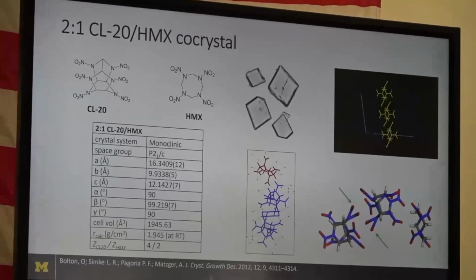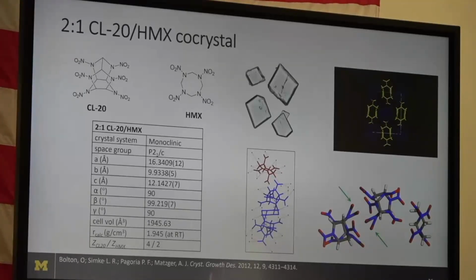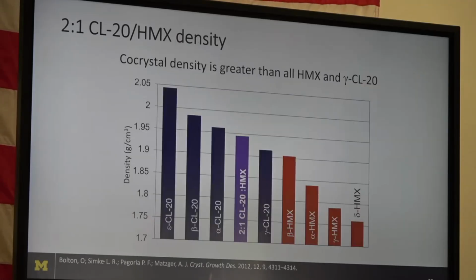The next really exciting energetic co-crystal that we made was CL-20 HMX. Now you're seeing an effect of stoichiometry. There are actually 2 CL-20s for every 1 HMX here. This is the crystal structure shown here and here, with a little bit of disorder. Again, the morphology is pretty nice. Of course, when we were doing this, CL-20 wasn't of as much interest as it is today. CL-20 is getting more interesting, so I think this is an interesting co-crystal as well. And it has been scaled up in flow by the Klapötke group, and probably others that I don't know about.